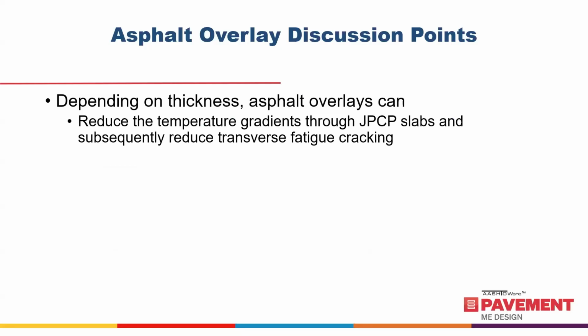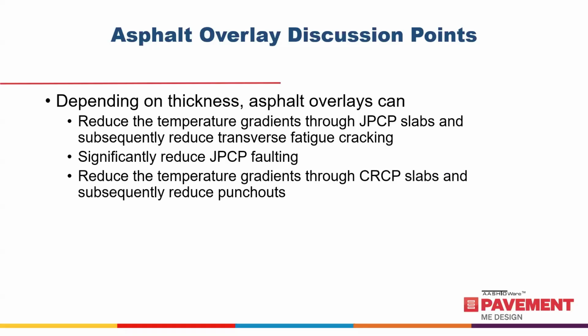So depending on thickness, and the other thing too is the overlays, the thicker ones actually can reduce the temperature gradients through the jointed plain concrete slabs, and thereby you're reducing really the curling stresses that occur, which contribute to increased transverse fatigue cracking. So the thicker asphalt overlays do help mitigate transverse cracking. And again, too, you can also reduce faulting as well, because you're not going to have a severe temperature gradient that could cause the joints to open up more. And then reducing the temperature gradients through continuously reinforced concrete slabs could also help prevent them opening up too much, and so you can actually reduce punchouts too with overlays.